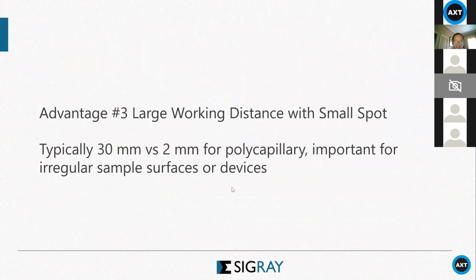So as you can see, if the surface changes by 1 millimeter, for us the focal spot only changes by 3%, but for polycapillary, it changes by a factor of 2, 50% in terms of the focal spot size. So it's very important for polycapillary. You need a polished, flat surface, and for our system, an irregular sample surface is just fine.